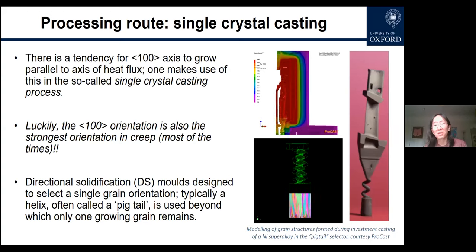As it develops, you can also do more interesting things about controlling exactly how you want the microstructures to be. Such ways are called directional solidification, and this evolved into the very important development of single crystal casting. What it does is solidify the material directionally, because we found there is a tendency of the 100 axis to grow parallel to the axis of heat flux. So we can use this to design a material that is quite anisotropic. And quite likely, as determined by nature, the 100 orientation is usually the strongest orientation in creep. So we are safe.